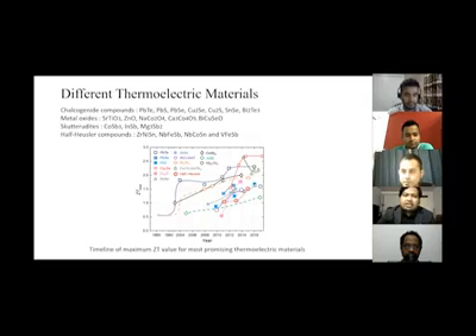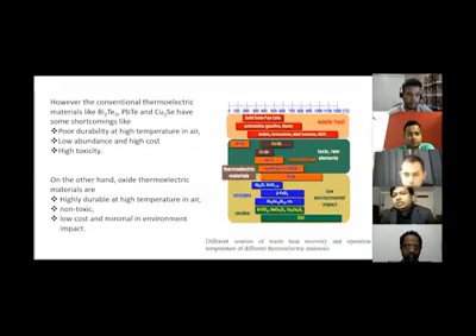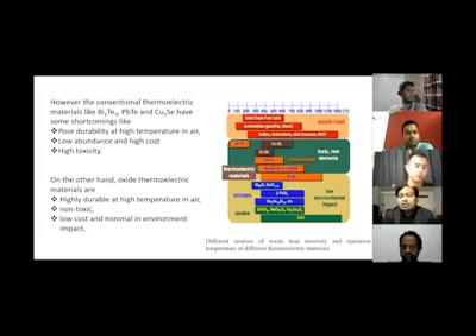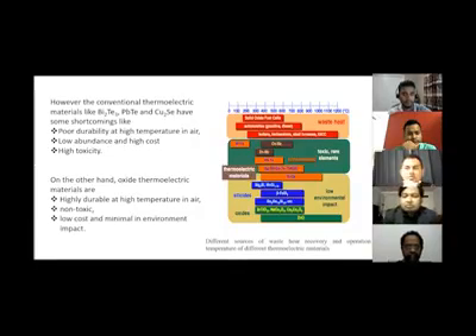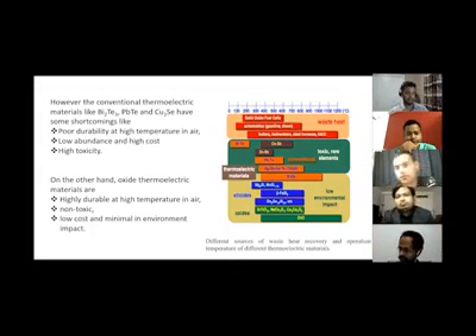Metal oxide based materials can also be used as thermoelectrics, which is actually my working field. I'm working on strontium titanate, lanthanum doped strontium titanate, as my thermoelectric material, because it is chemically robust at high temperature, available and non-toxic. So if we think about green energy or sustainable energy, then I think metal oxide is a good alternative compared to the commercially available bismuth telluride or lead telluride. They are also good and their performance is good, but they are not stable at high temperature and some of them are toxic. So metal oxide could be an alternative to other materials.